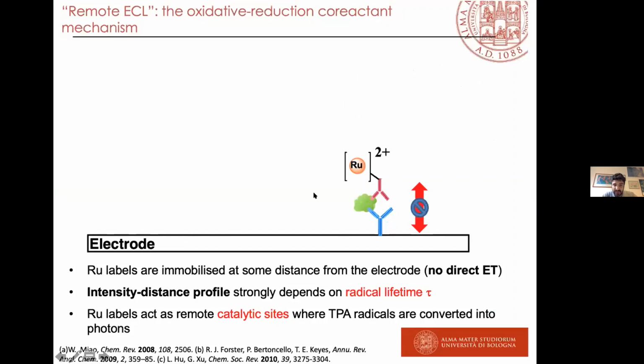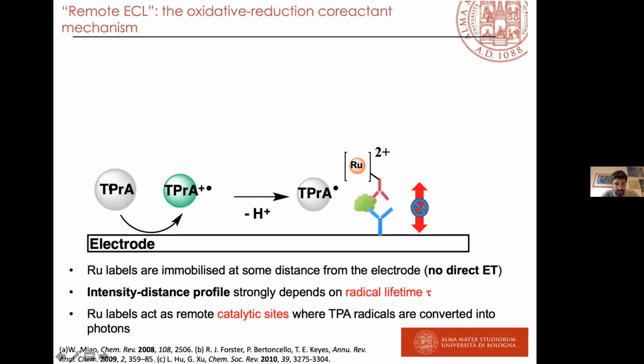So what occurs at the electrode surface? You can see here I schematized the immunoassay system, the detection antibody labeled with our ruthenium tris(bipyridine) complex, capture antibody, analyte, everything on the electrode surface. You can have this on the electrode surface or on beads. Those are two different approaches, but the same mechanism. And coreactant: you can oxidize the coreactant, you can generate a radical cation, and this is an unstable radical cation, and you can have a classical electrochemical-chemical mechanism where you are degrading the radical cation to the radical, and you have both of these in the diffusion layer.